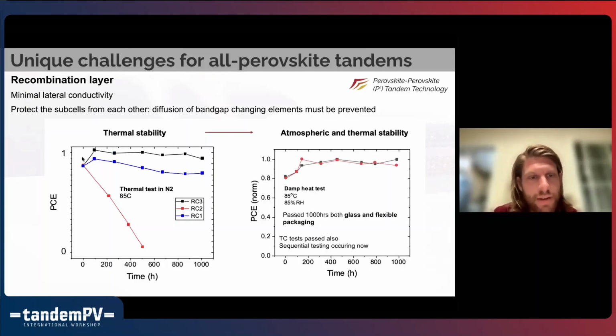Then once you have this kind of result, you can start doing damp heat testing. We have done damp heat testing now of our tandems, both glass packaging and flexible packaging, which to our knowledge is the first demonstration of flexible perovskites passing these sorts of damp heat tests. As others have said, it's important to do multiples of these tests, so that's ongoing. Even more important than doing multiples of the tests is also, I think, doing sequential tests. For example, doing damp heat testing after thermal cycling to see if any of the adhesion points in the module have failed, and now it's susceptible to moisture ingress. Those are also happening at the moment.